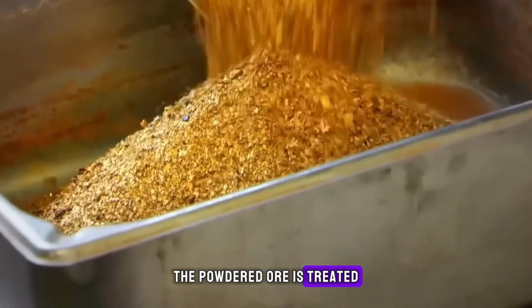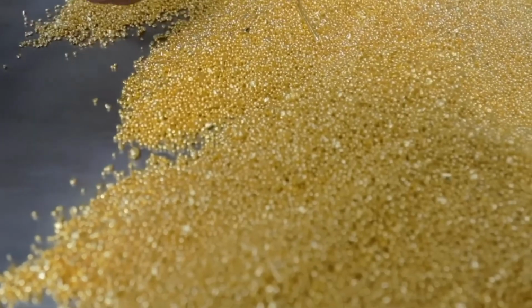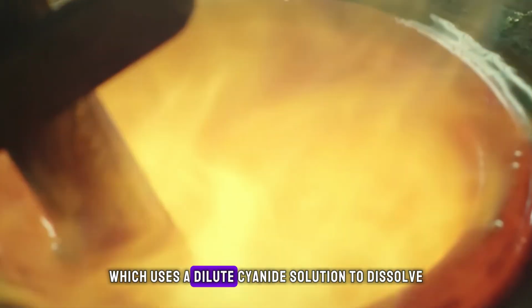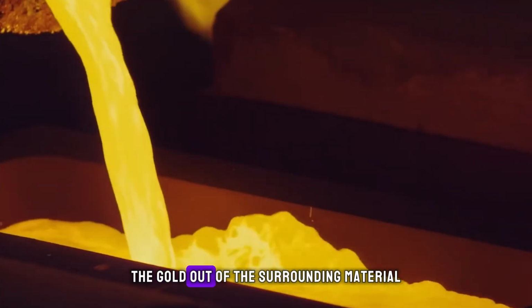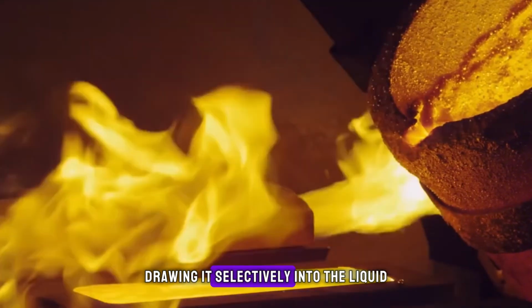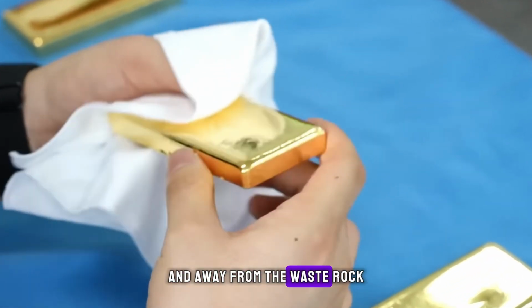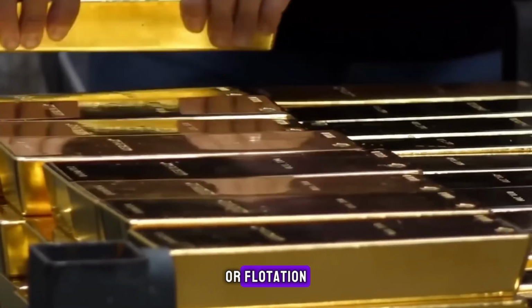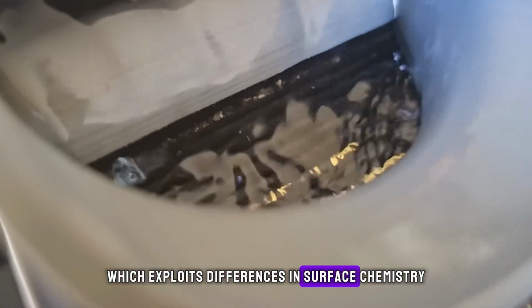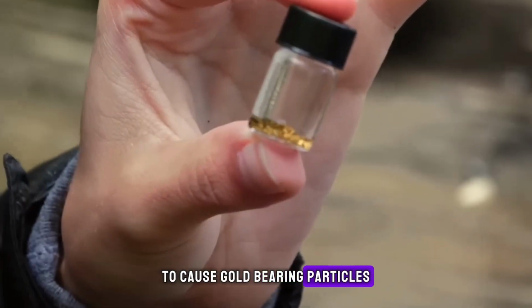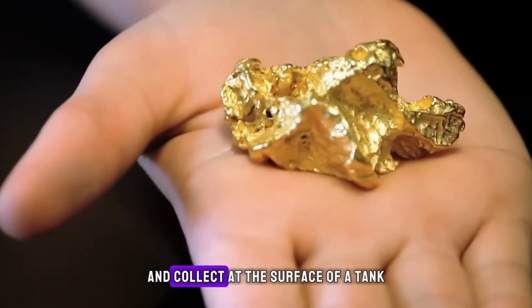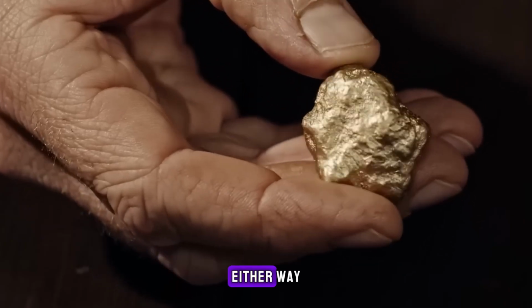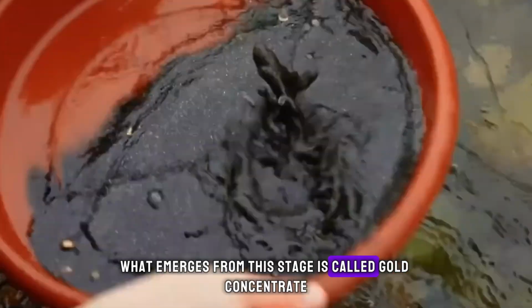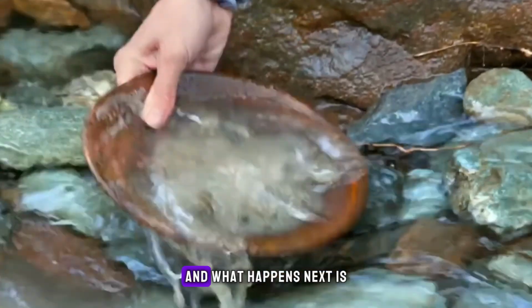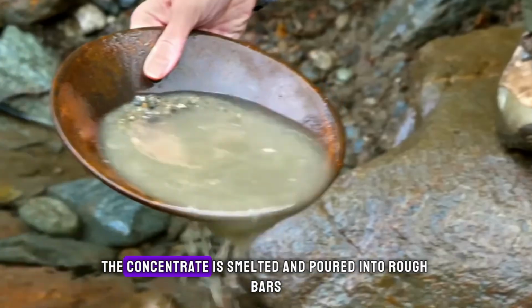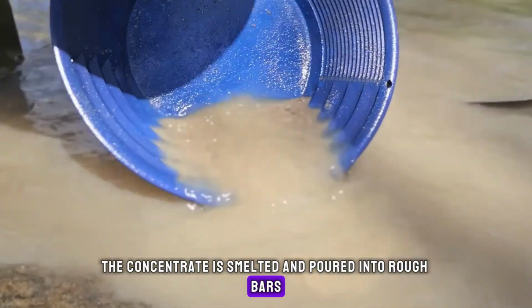The powdered ore is treated through one of two principal methods: cyanidation, which uses a dilute cyanide solution to dissolve the gold out of the surrounding material, drawing it selectively into the liquid and away from the waste rock; or flotation, which exploits differences in surface chemistry to cause gold-bearing particles to attach to rising air bubbles and collect at the surface of a tank. Either way, what emerges from this stage is called gold concentrate. And what happens next is the concentrate is smelted and poured into rough bars known as doré.